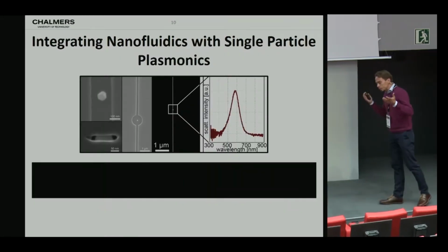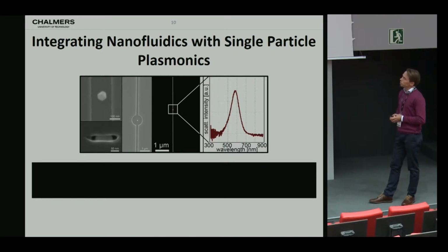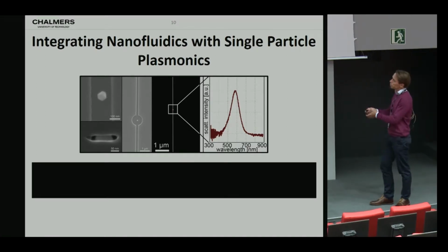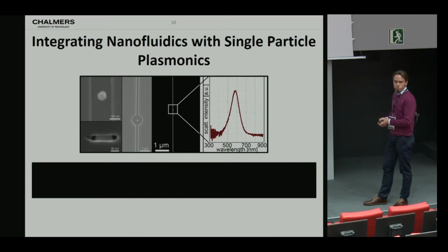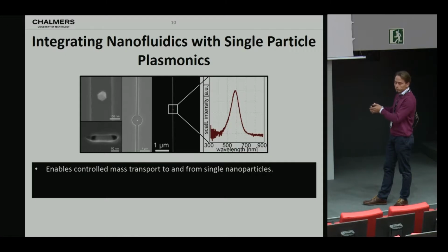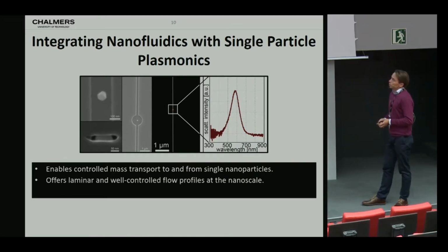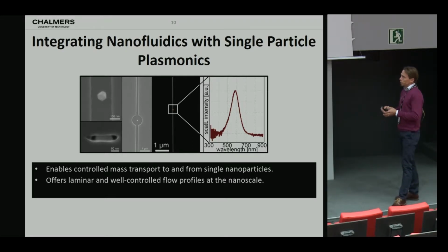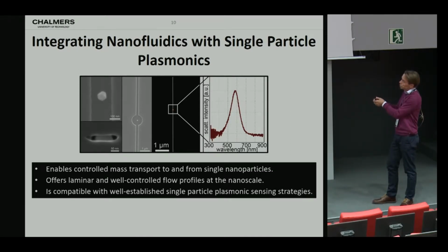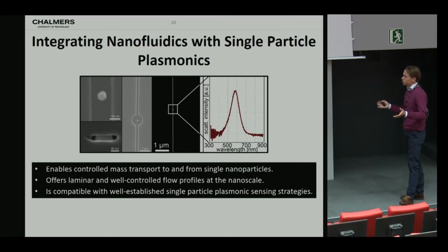And this is basically some of the motivation behind why we have started looking at integrating nanofluidics with single particle plasmonics in a way that is shown here. So what we're doing is we make nanofluidic channels and put nanoparticles into them. In this way, we are enabled to control mass transport, as I will show you, in the liquid and in the gas phase, to individual nanoparticles, but also away from individual nanoparticles. Interestingly, the flow profile in these nanofluidic systems is typically of laminar nature, so we have very well controlled mass transport. And as you can see already from this picture, this is compatible with well-established single particle plasmonic sensing strategies like dark field scattering spectroscopy.